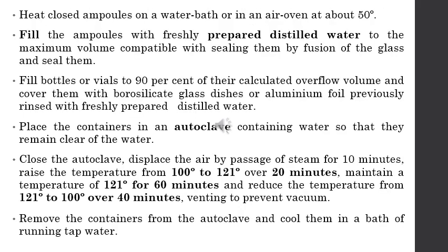Now we can have ampoules, or we can have bottles or vials if we are using glass as a material. So if we are using ampoules, we have to fill it with water first, which is freshly prepared distilled water, and then seal it by using various methods. Then if it is a bottle or a vial, we have to fill up to 90% of the overflow volume and cover them with borosilicate glass or aluminium foil which is previously rinsed with distilled water.